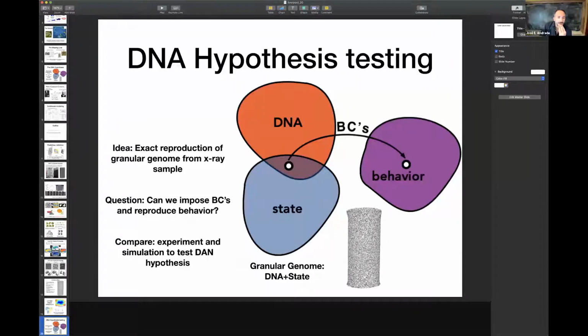And then the question is here, can we impose the state, you know, the same confining pressure, for instance, as in the experiment and the same density as in the experiment, and then probe with the same boundary conditions and obtain the behavior that we see in the experiments? And by behavior, again, I want you to think in an expansive way now, not only macro stress strain, I'm talking meso and even micro, right, granular scale with the kinematics.